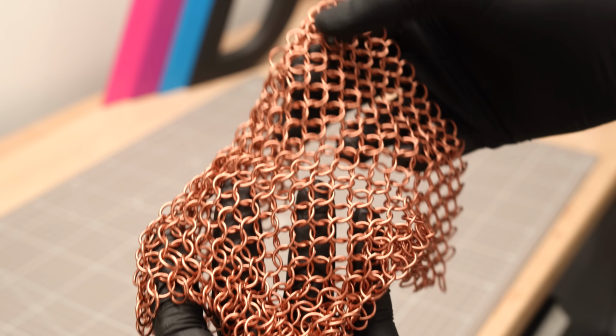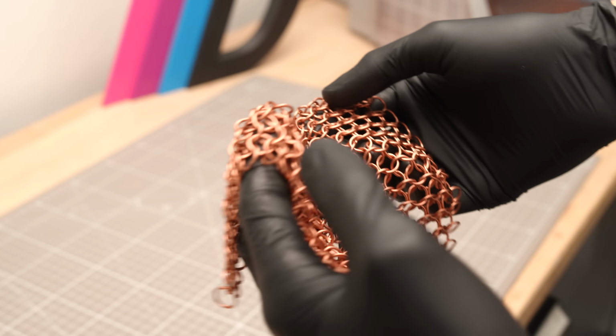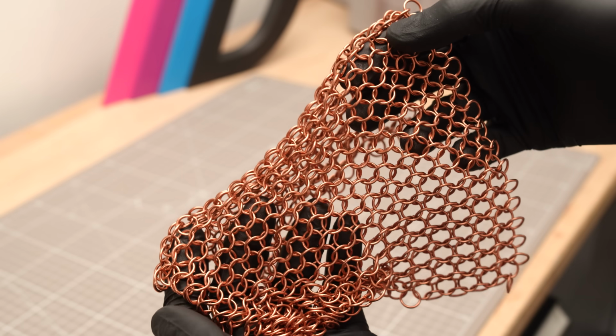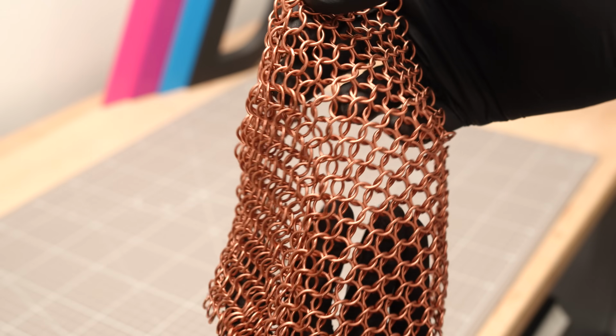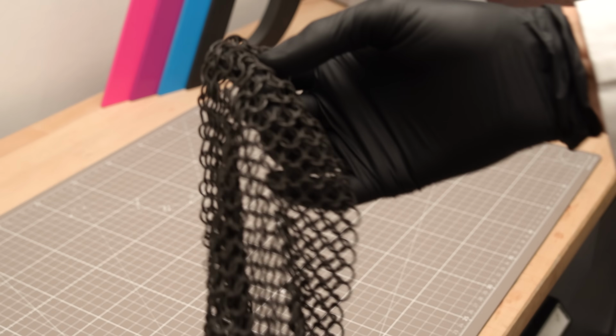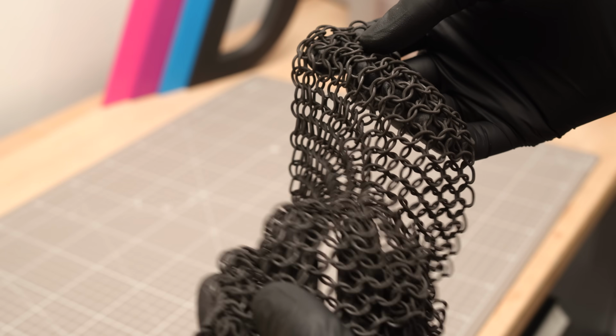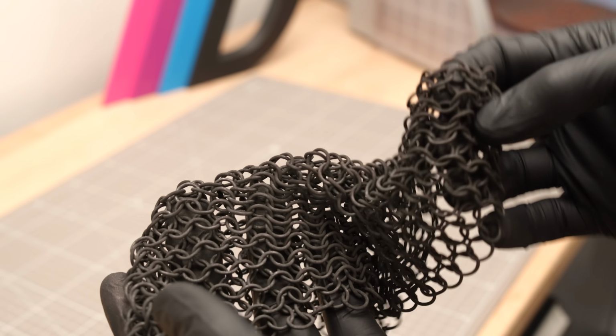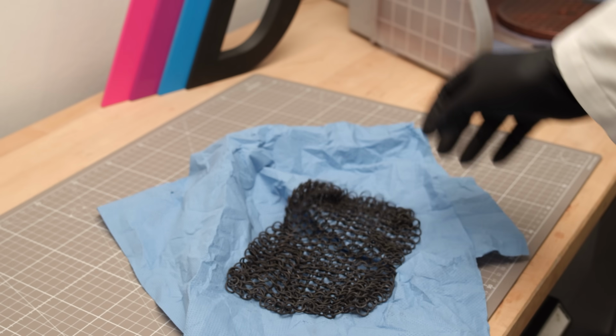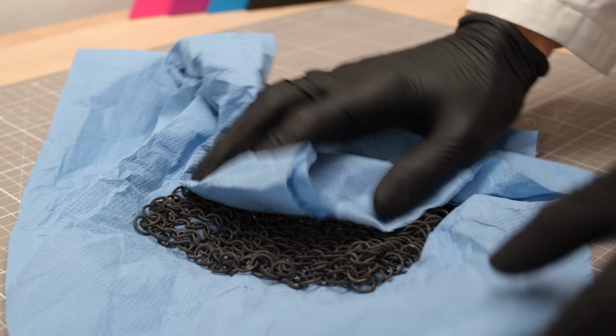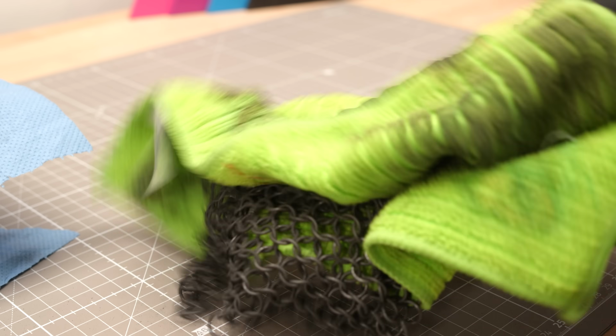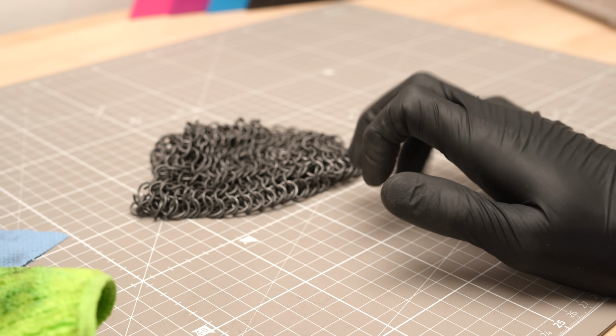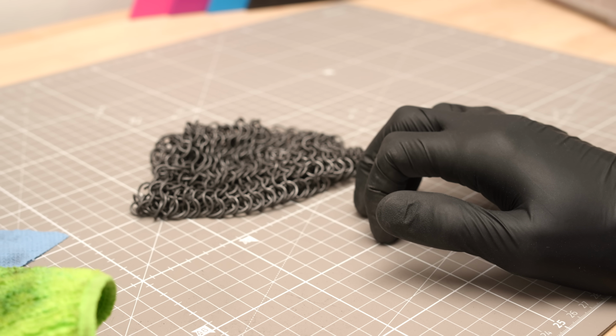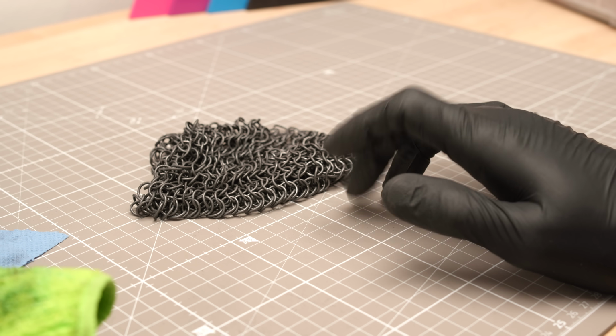Now check this out. Here we've got a hopefully evenly coated chainmail, and if it's not conductive yet, don't worry, once it hits the electrolyte, it will be. The graphite coated chainmail still has a bit too much resistance though. You can fix that by polishing it. First, I wipe off all the loose graphite with a paper towel, then I go over it with a microfiber cloth to really shine it up. And surprise, still not conductive enough. Ideally, you want the resistance to be under 1 kilo ohms.